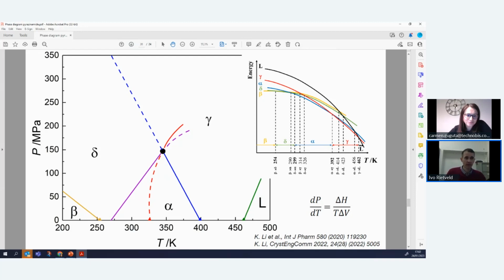So in fact, by DSC, for all the measurements that we did under room temperature conditions and slightly above, slightly below, there was no conversion. And within the vapor pressure measurements, we kept within the transition points that we saw within the DSC. So in principle, everything should have worked out fine. But there is always a risk that something converts in the meantime.